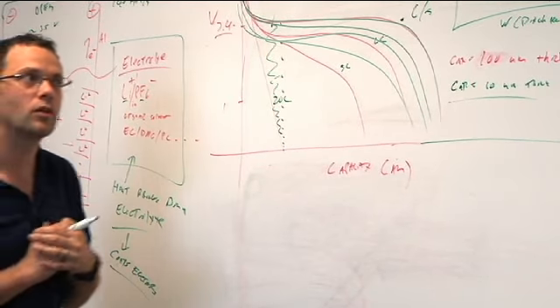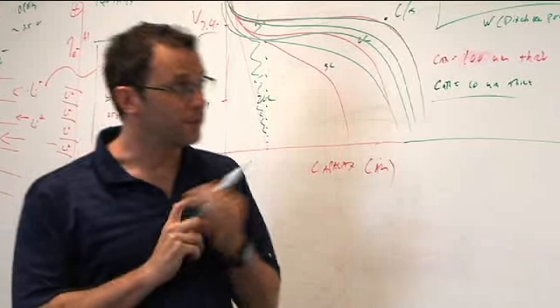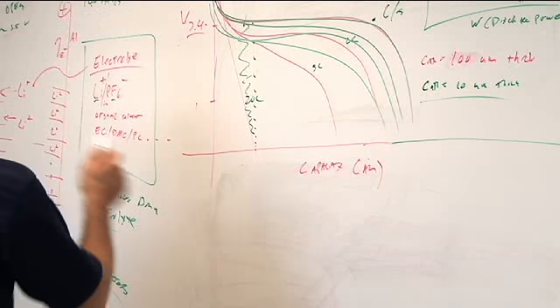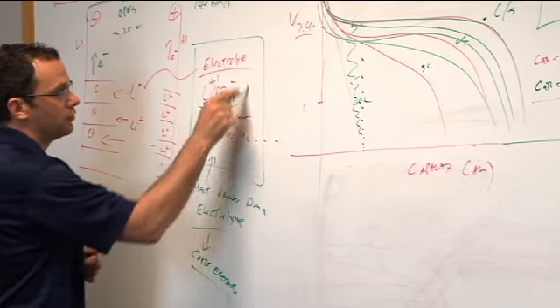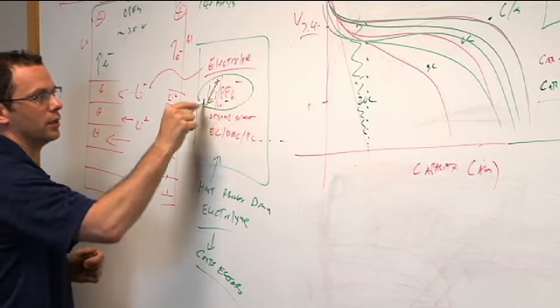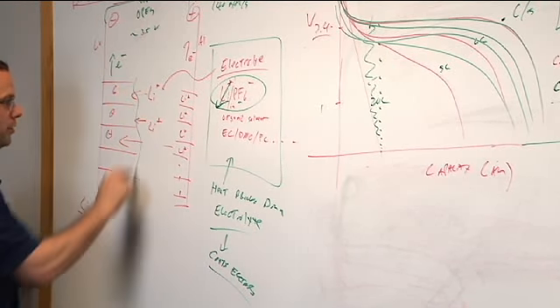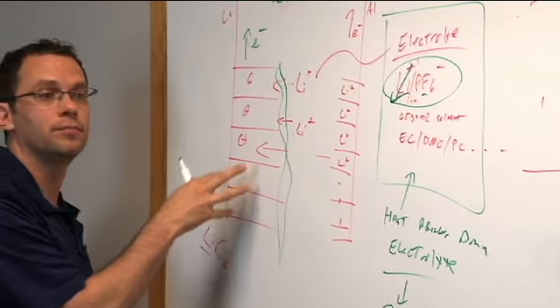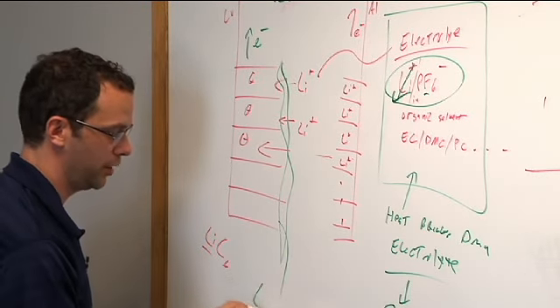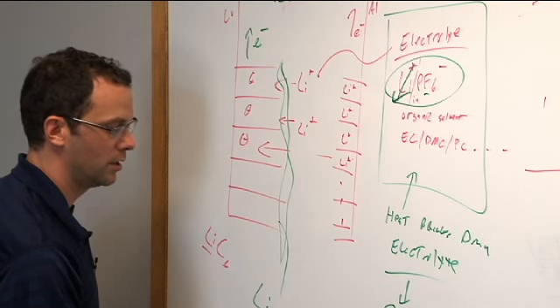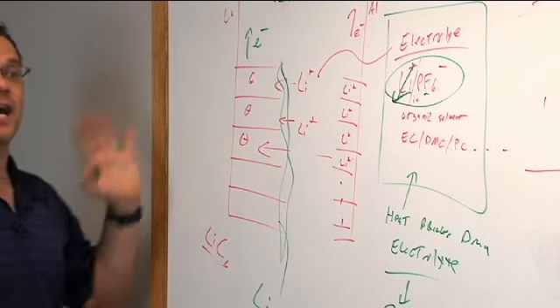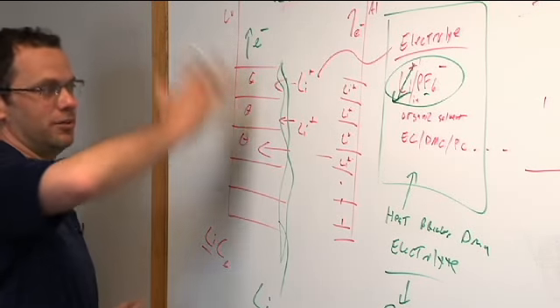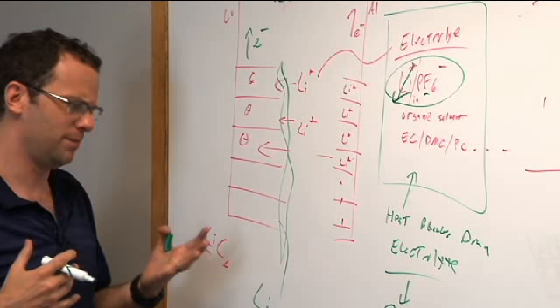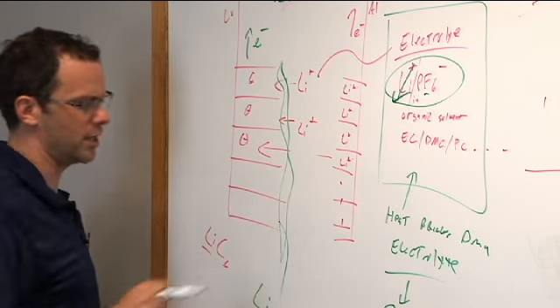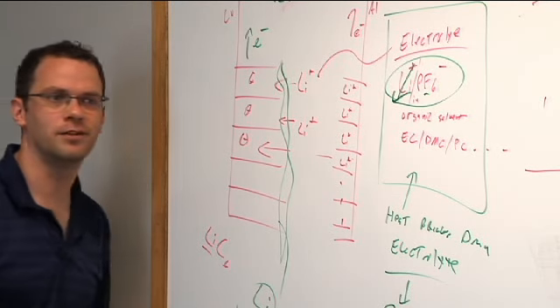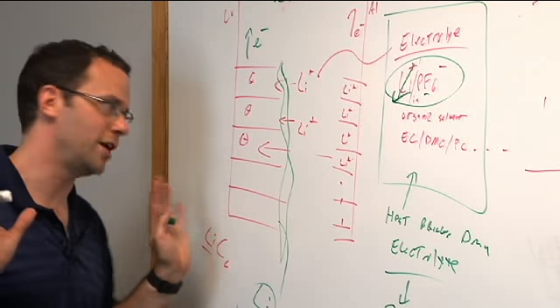What's the degradation mechanism of the batteries? Why does my battery lose capacity? Lithium from the electrolyte leaves the electrolyte and forms a coating on my anode. And the coating, as a placeholder, is lithium carbonate. So it's not intercalating anymore. It's out of play, right? It's a relatively resistive, benign coating, but it's resistive, and then it resists lithium transfer. But most importantly, it ties up this lithium, and that lithium's out of play. And you can't get it back out, right?